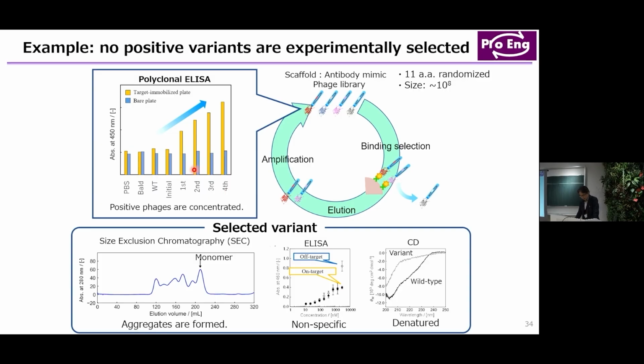However, we separated about 100 variants from the second round sub-libraries, but we couldn't find a good variant with good structure. For example, this variant shows many morphologies of structure like that. The important thing is that this selected variant shows aggregate forms. Further, this variant shows non-specific binding for protein, and this fragment has no secondary structure.